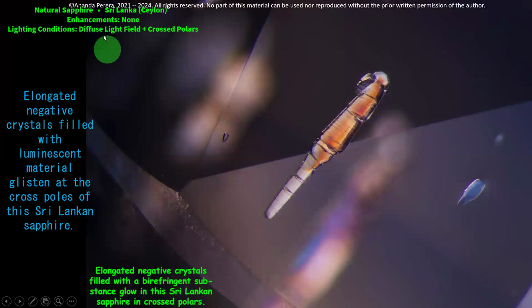What is this? What are the lighting conditions here? Diffuse light field plus crossed polars. Look at the elongated negative crystal here. Another negative crystal. This one is an elongated negative crystal filled with luminescent material. Luminescent material is inside, glistening at the crossed polars of this Sri Lankan sapphire. So crossed polars give us this image, proving it is not a treated one, it is a natural gemstone.